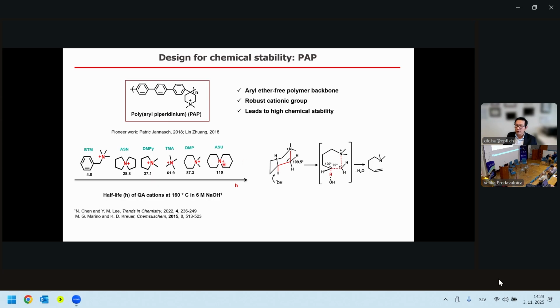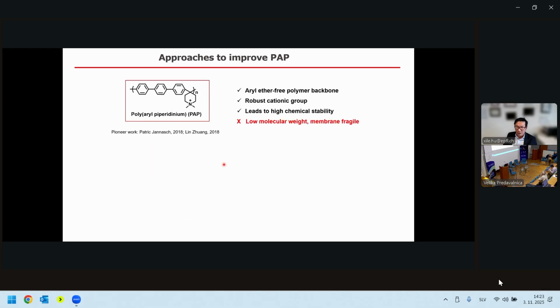Based on these considerations, people have been working on this new generation of membranes. However, they are not really practical because these polymers are difficult to grow. If you know membrane chemistry or polymer chemistry, you know that to have a good membrane, you need a high molecular weight. And these ones actually cannot achieve it. And so then you cannot get a good membrane for use, right? So how do we solve this?